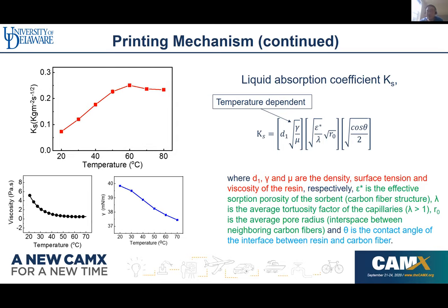You can see the green color is about the carbon fiber geometry. If we change from the carbon fiber filament to a tape or to a fabric, we can create different tortuosity, and different key numbers like the R0, with different carbon fiber diameters. So in this case, we can also change our liquid absorption coefficient Ks. And the third one, the blue color, is the contact angle. The contact angle indicates the interaction, or relationship, between the fibers and the liquid resin.